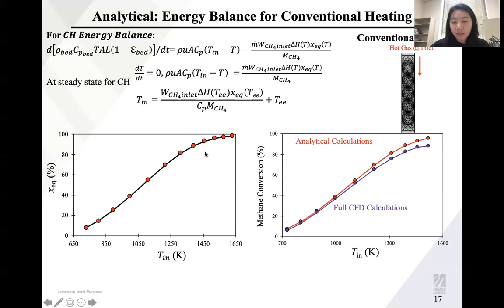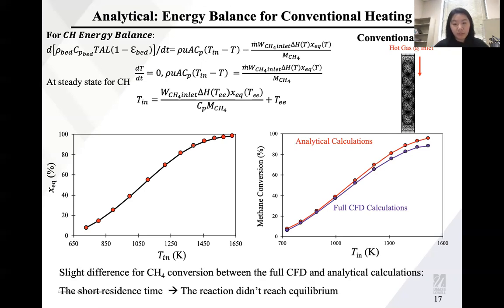And we compare with our full computational fluid dynamics simulation in COMSOL Multiphysics. We found the majority agrees with our analytical calculations, with just a slight difference. This difference can be because the residence time of this catalyst bed is not long enough to fully finish this methane steam reforming reaction in this reactor.